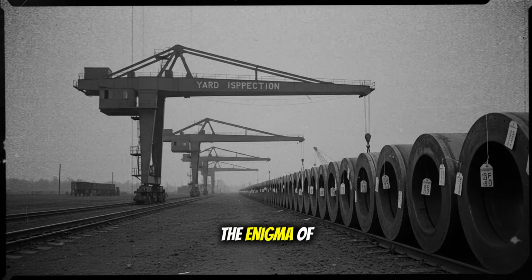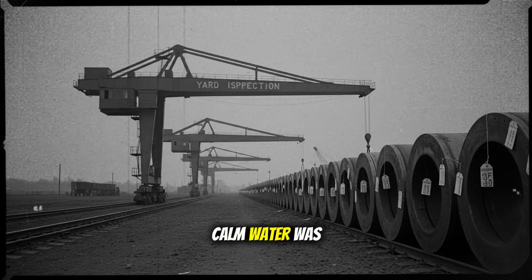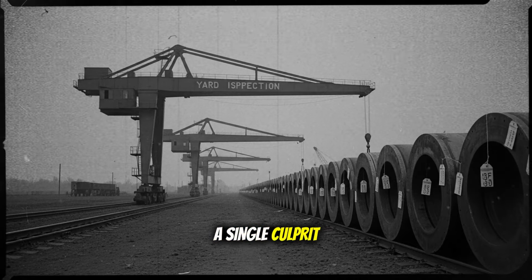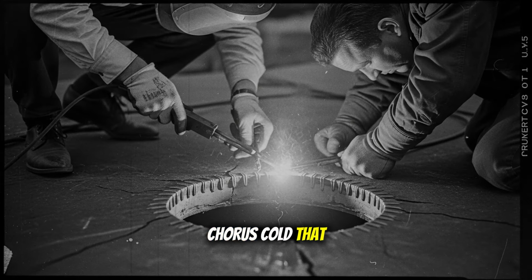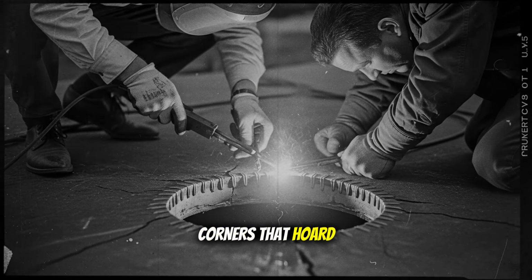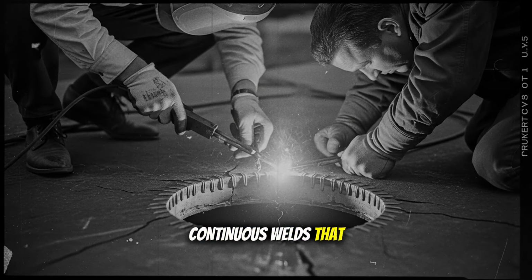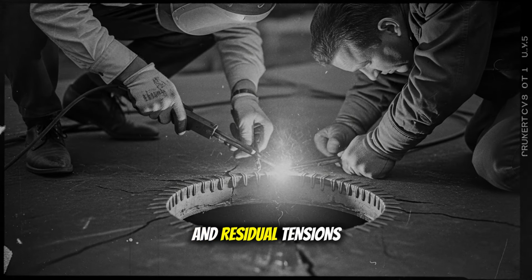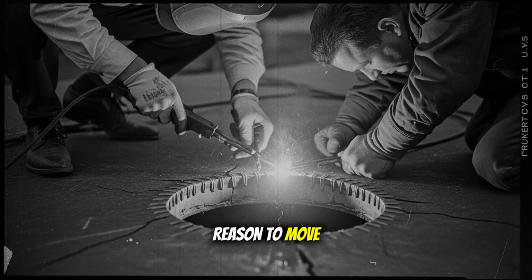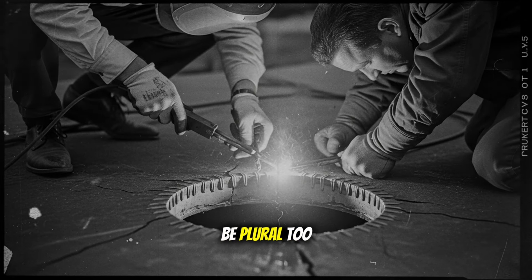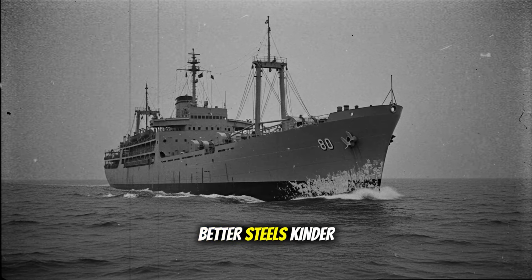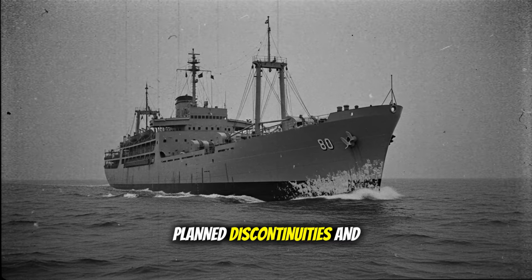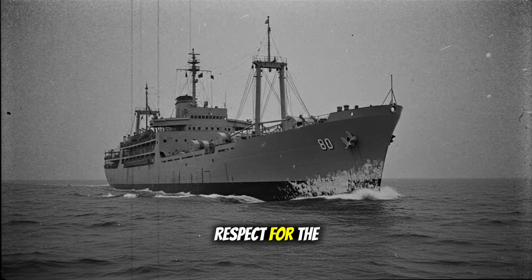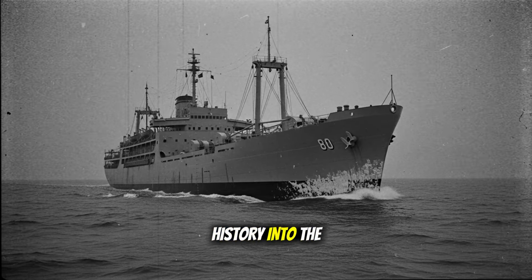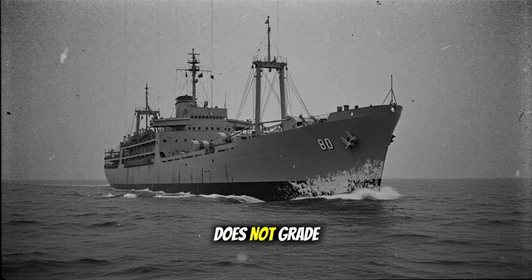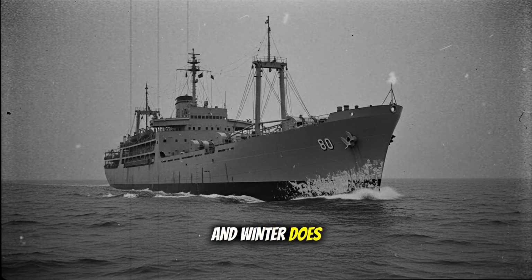In the end, the enigma of ships that broke in calm water was resolved not by a single culprit but by a chorus: cold that steals ductility, corners that hoard stress, continuous welds that offer a perfect road, and residual tensions waiting for a reason to move. The cure would be plural too: better steels, kinder geometry, planned discontinuities, and a new respect for the way welding writes its own history into the metal, because the ocean does not grade on a curve, and winter does not negotiate.